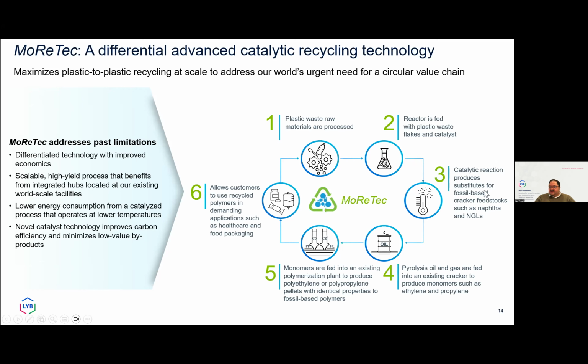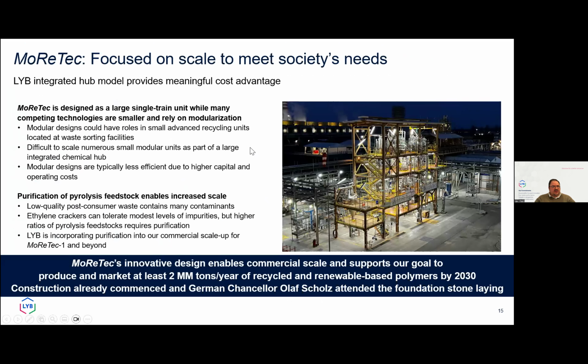And after having reduced with catalytic production or cracked the chains, we come out with pyrolysis oil and gas, and that is fed into the existing crackers we have. And the crackers, if you look into the literature, crack down those already pre-cracked molecules into C2, C3, which then can polymerize to polyethylene or polypropylene. And then, this is very important, identical properties to fossil-based polymers. This is why it is a drop-in solution. And then you can use these recycled polymers in demanding applications such as healthcare and food packaging, which is very hard to achieve with mechanical recycling. But mechanical recycling is complementary, as I said, for example, for industry applications.